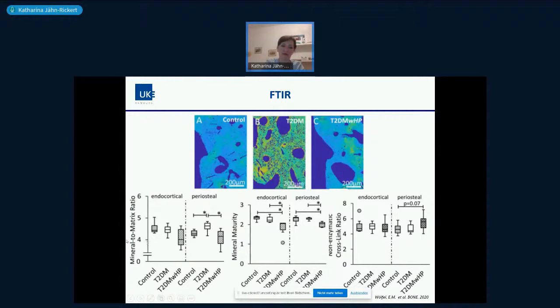There's one that shows you what the mineral to matrix ratio is, so how much mineral you have, relatively speaking, in your specimen. You see here on the periosteal side that the type 2 diabetic specimens had a quite higher mineral to matrix ratio compared to the other groups. There's also a way to look at the maturity of the matrix, so whether the hydroxyapatite crystal is really mature already. One could see that both at the endocortical but also at the periosteal side, the high porosity group had a lower maturity, speaking for a younger, more remodeled bone, which makes sense with the high porosity.